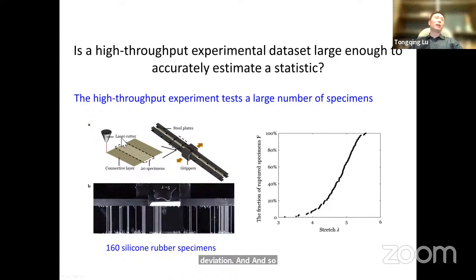So now we conducted another high throughput experiment. Here we use silicone rubber. We also measure the rupture stretch of 160 silicone rubber specimens. Here we use a laser cutter to prepare the samples, which is also a very efficient way. So we have this CDF as a function of stretch, with 160 points here.